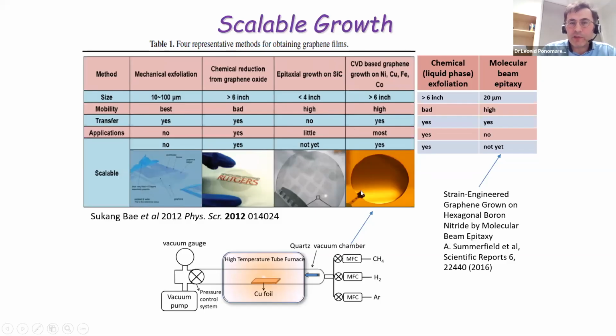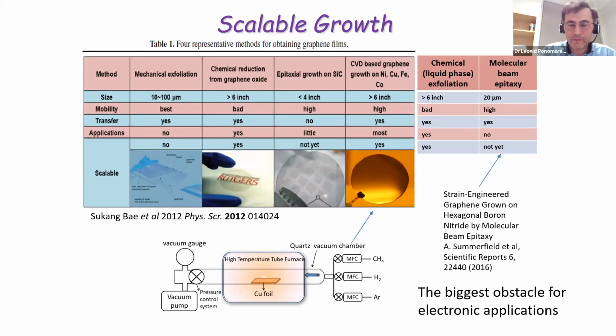But the highest mobility achieved with this method, and this has been the case for quite a few years, is only 3,000, which is not enough. And the graphene obtained on such wafers, which is actually transferred onto wafers from copper foil, is not a monocrystal graphene, but many, many polycrystals grown and overlapping, merged together. So the absence of a scalable production method is the biggest obstacle at the moment for using graphene in electronics applications.